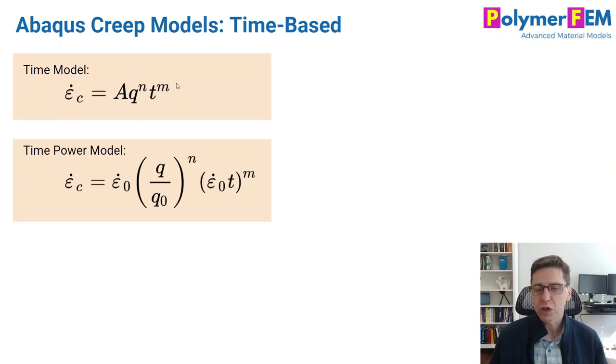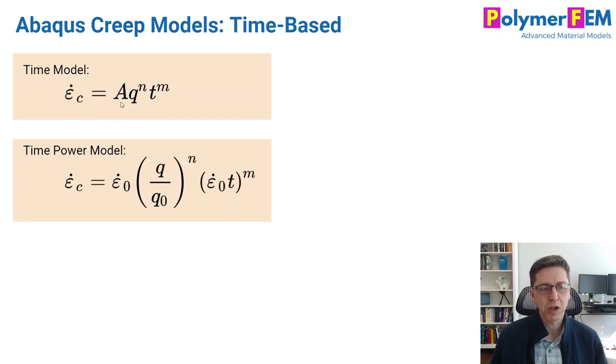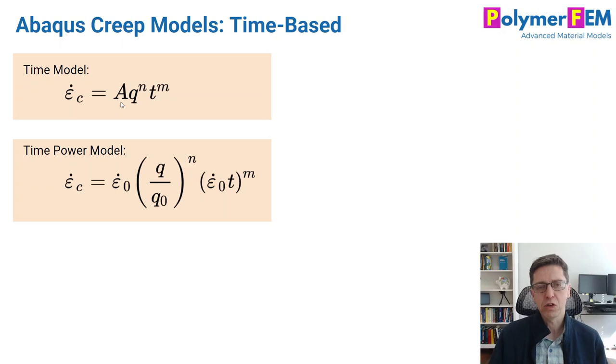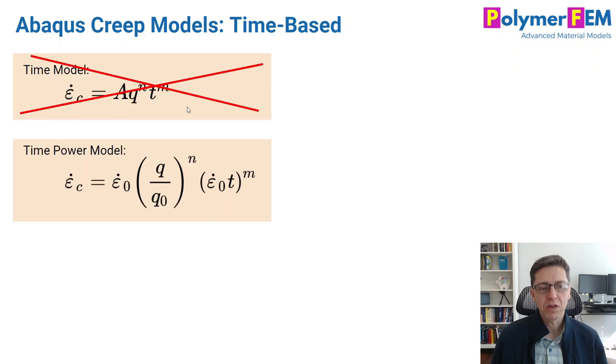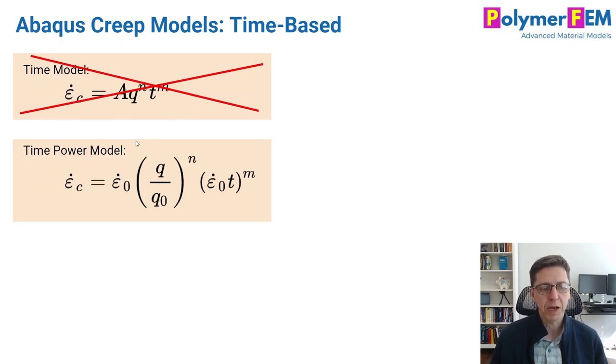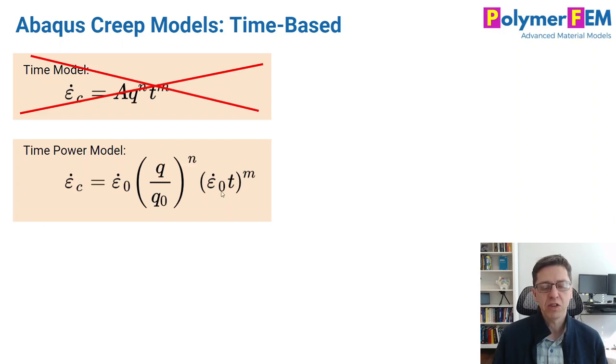In order to make this work, you would have to have a tiny, super small number that's very close to zero, causing issues with floating point numbers, etc. So when it comes to using this, you should not use the time law, you should always use the time-power model because of that issue. It's normalized, the units are correct, it's just a better formulation.